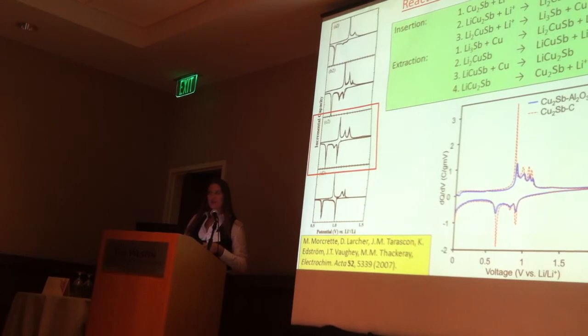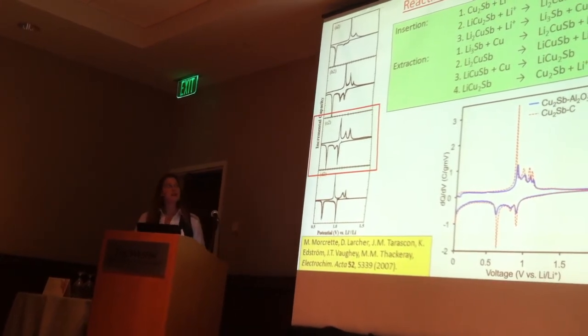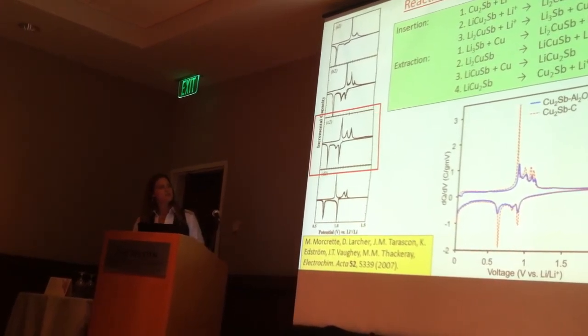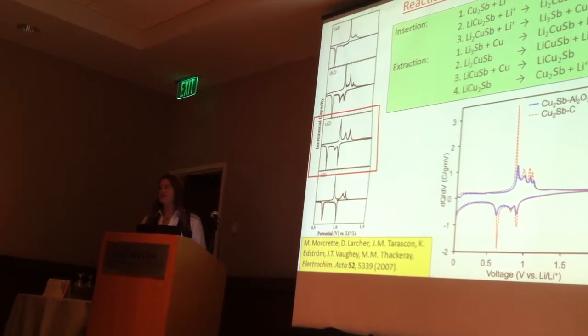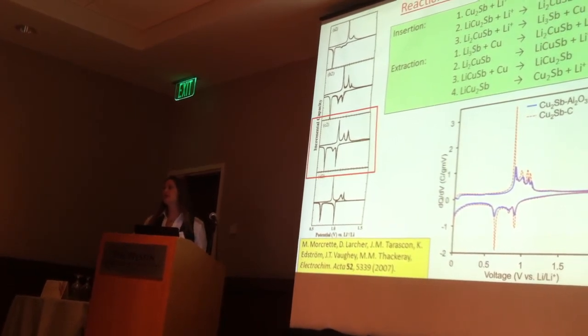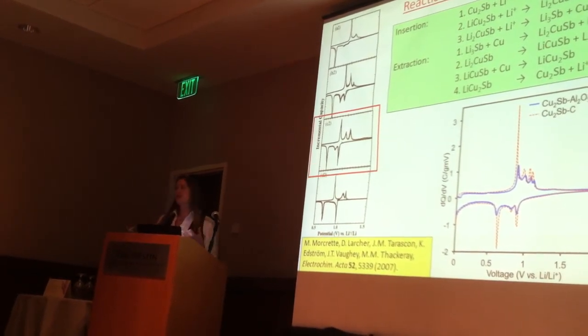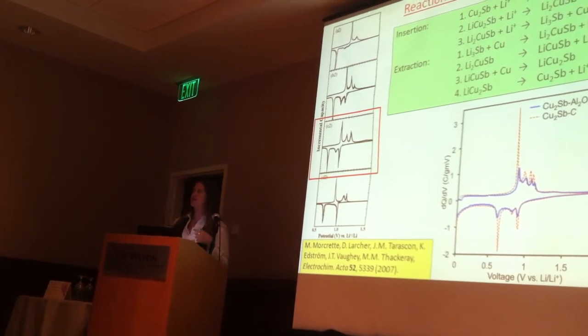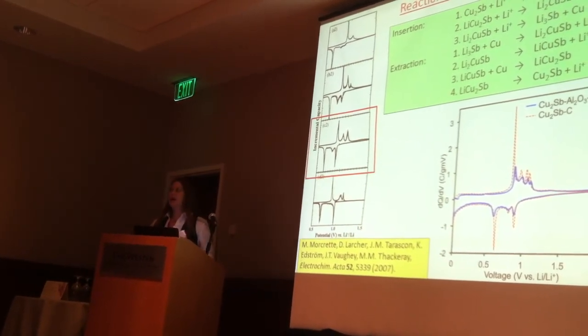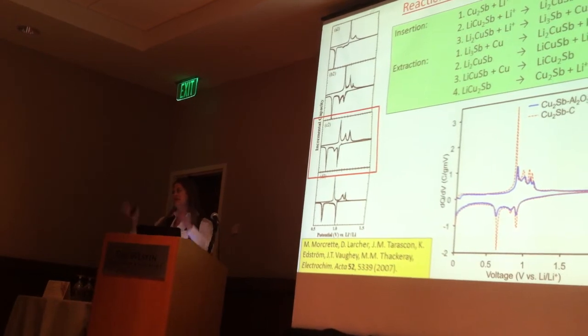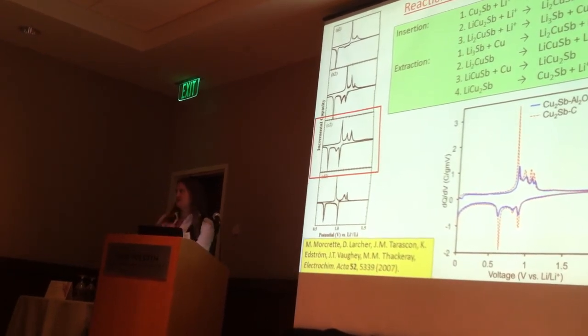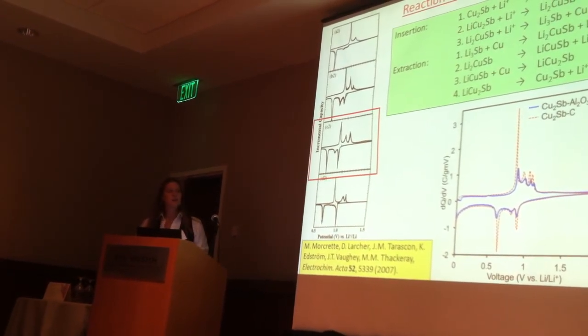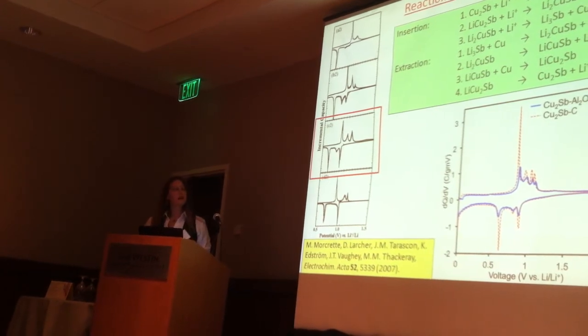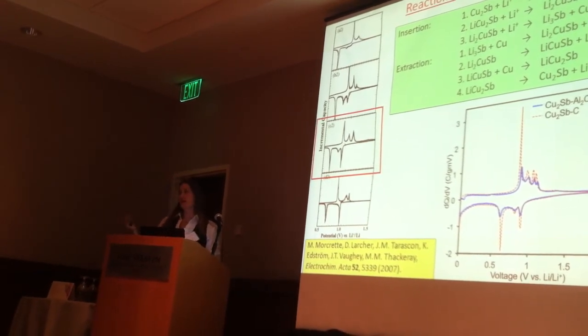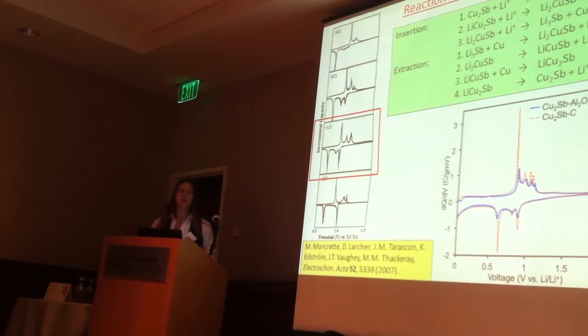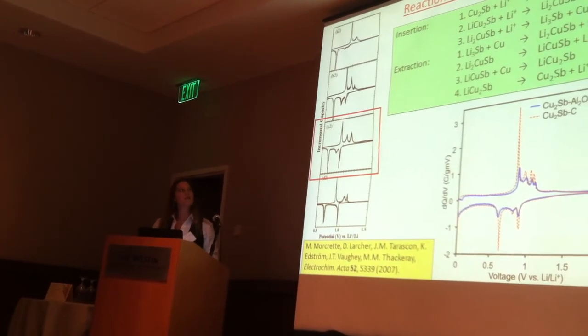So our big unanswered question for this material is actually pretty interesting to me. What is the reaction mechanism? These particles are small, so when we look at them with XRD, if it's ex situ XRD or in situ XRD, we're not able to see the crystalline phases because the peaks are very broad, the particles are so small, we can't differentiate phases. And so we also tried high-res TEM, and the resolution for d-spacing wasn't really enough for us.